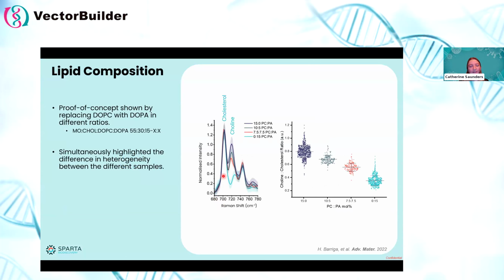So we can start off by looking at the average spectra. And what you can see is that the cholesterol amount was kept constant, and then the PC or the choline amount was changed. So in the average spectrum, the cholesterol peak is very stable, and then the choline amount is changing on average as we switch over from the PC to the PA. And then if I break out into the single particle information, we've got the univariate plots over here. And you can again see the average line is decreasing, but the whole population is decreasing as well.